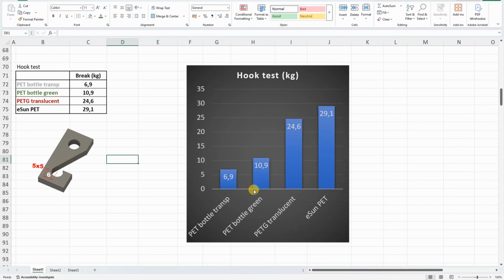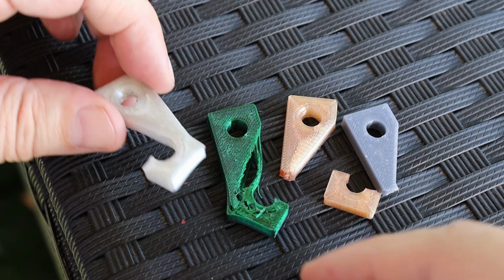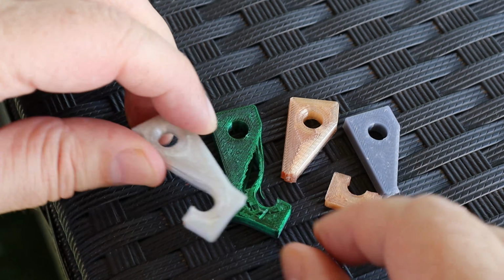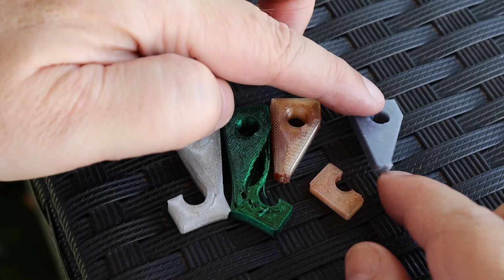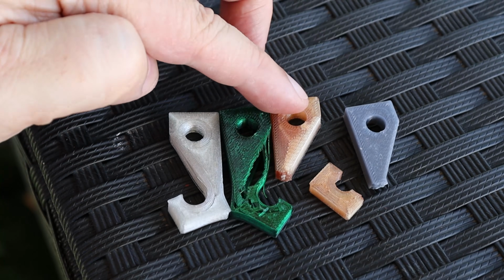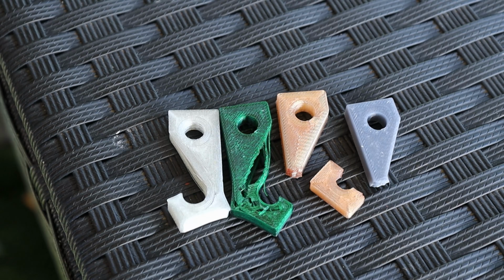And again, the two recycled PET filaments are much weaker in this case compared to the PETG or eSun PET, and a main reason for this is not the material property but the underextrusion during the printing. This results in not only weak layer but also weak wall adhesion, which is important in this case. And this is how a healthy break should look like, with these hooks.